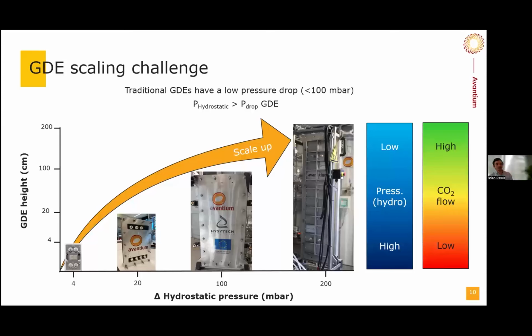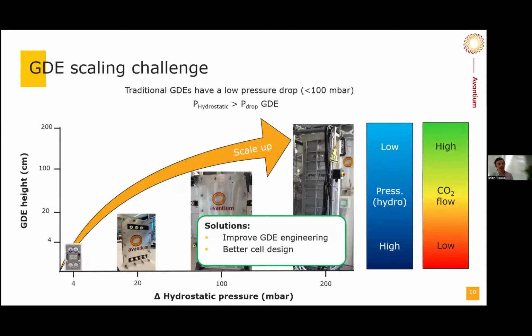So what we see is that as you have a 2 meter high electrode, you have a hydrostatic pressure regime, low at the top and high at the bottom. And what happens is that the CO2, the gas, has a preferential pathway toward the top. So some things that need to be improved here are cell or GDE engineering to improve this distribution of gas evenly throughout your GDE. That's something that we're working on in the WaterProof project to improve on.